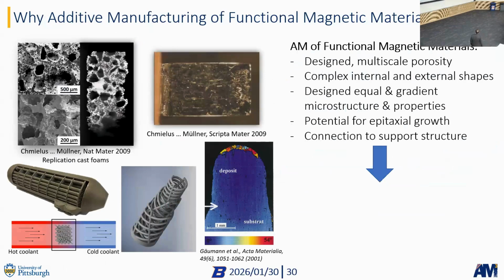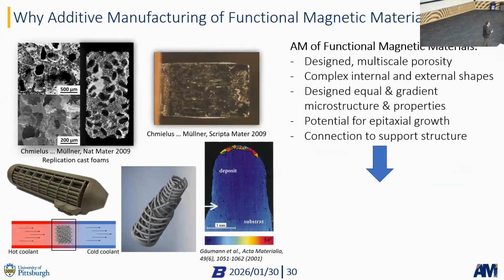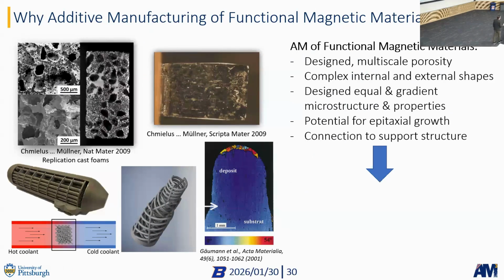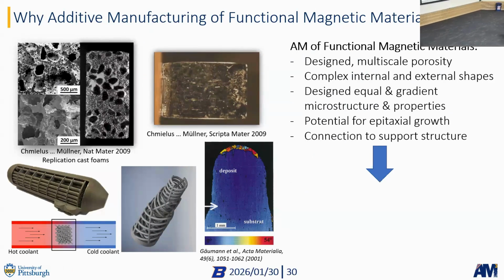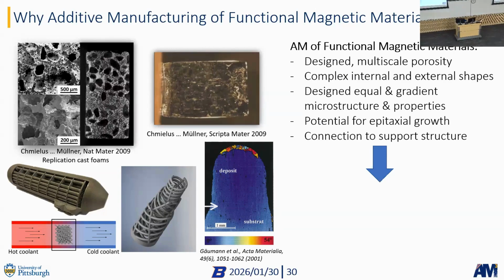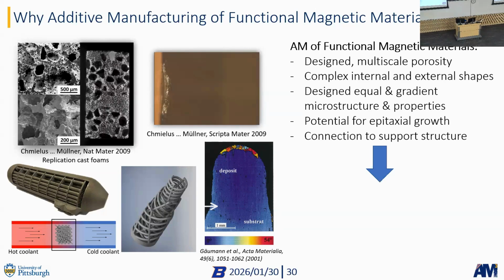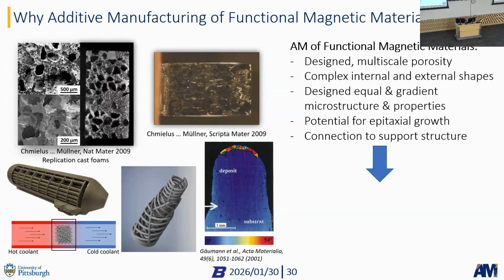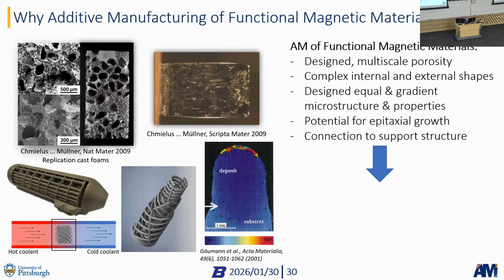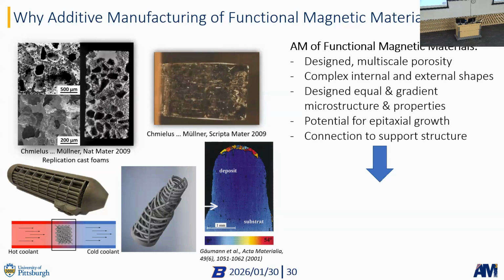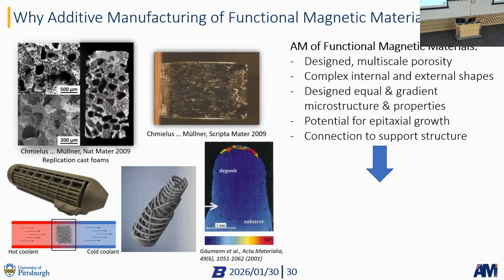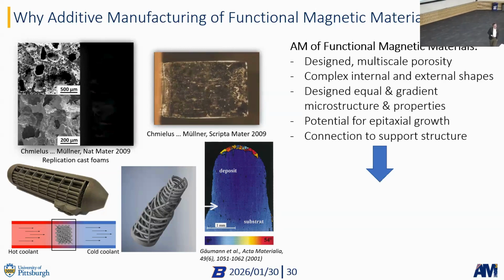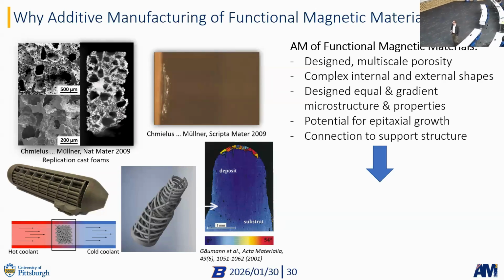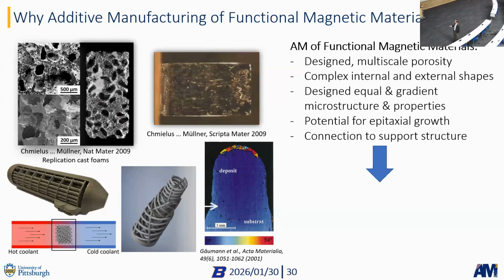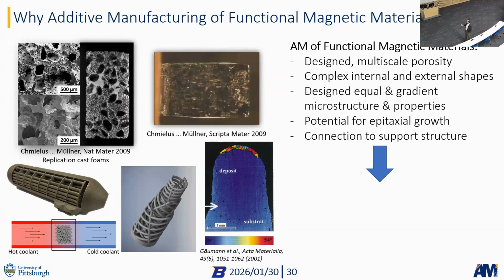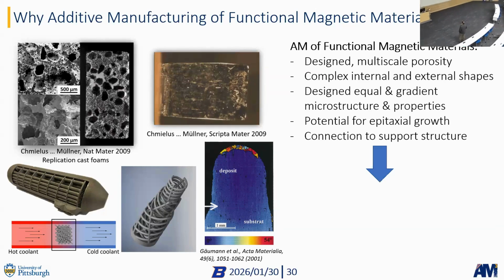So for additive manufacturing, what I really looked at was designing multi-scale porosity, right? I looked at, can we actually print very complex shapes, because these materials are fairly brittle. And so when you want to machine them, they can break very easily. Also, for certain additive manufacturing techniques, you can manufacture gradient or equal compositions and therefore functionality. So that could be for direct energy deposition, for example. We can potentially grow epitaxially. So we can grow single crystals using direct energy deposition. And we can connect our structure or functional structure here to the support structure so that something like this does not happen, right? That our functional material flies away.